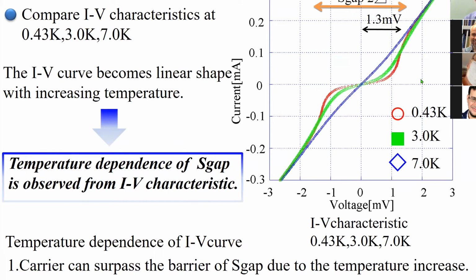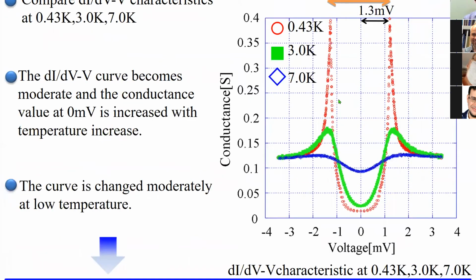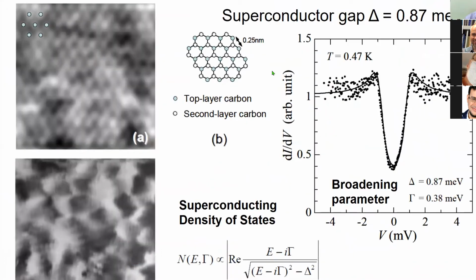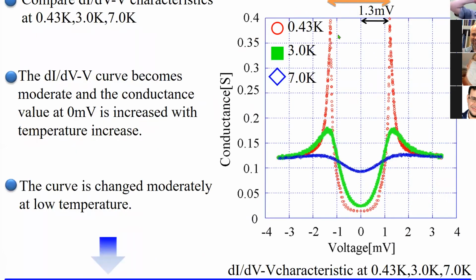Before that, we measure the superconducting gap, which is not published yet, but it's interesting. We measured the superconducting gap using the IV characteristic, and the gap we get is about 1.3 millivolts, which is also expected from scanning tunneling spectroscopy by another group, but on our sample. They measured 0.9 or 0.87 milli-eV, which is almost the same. This is just a simple measurement using an aluminum oxide and aluminum probe, but it's very reliable, and very easy to measure the superconducting gap from the IV characteristic.